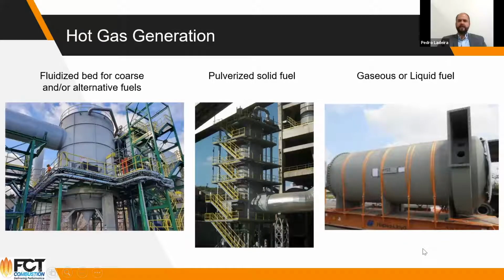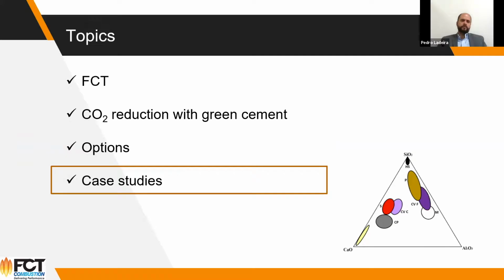As for the hot gas generation, the source of heat, you can use simple gaseous or liquid fuel hot gas generators, pulverized solid fuel, or even the fluidized bed for coarse and alternative fuel. So it all depends on the availability of fuels and the flexibility you want to have. I'm especially excited about using this technology of the fluidized bed because, again, no moving parts there. It's static equipment. You don't even have to grind the solid fuel up front. So you can really rely on very good control, good thermal inertia and very precise temperature control. So these were the pieces of equipment available. It depends from case to case.